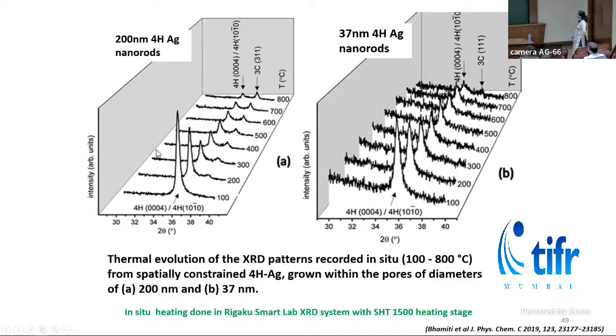From this XRD data, we can see that at 200 degrees centigrade itself, some wires have started changing to 3C. As we go on heating the sample, by 800 degrees centigrade, most of the wires have already converted to 3C phase. So 200 nanometer wires are not stable.